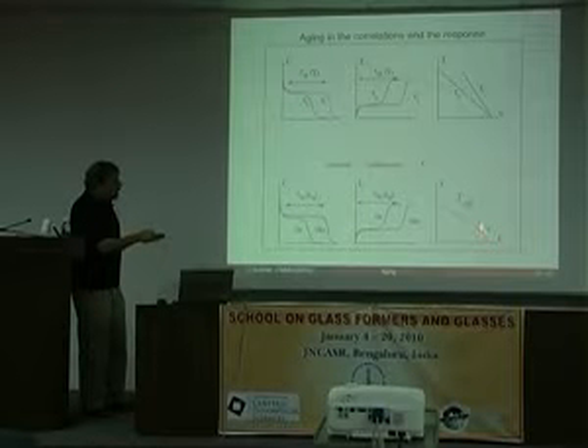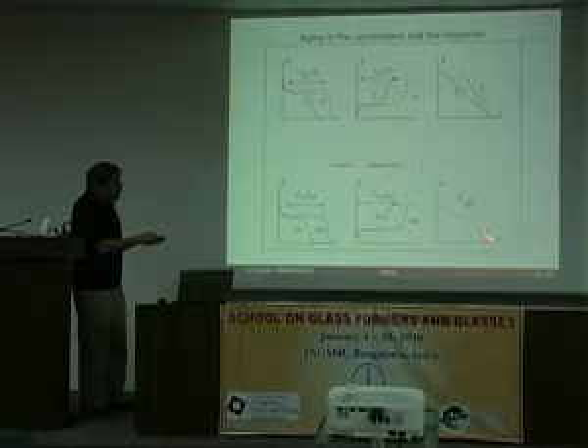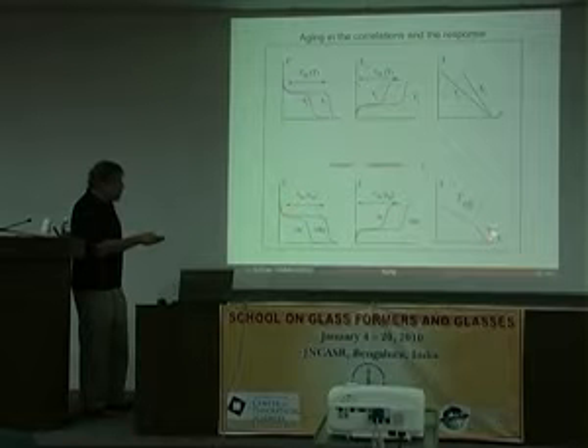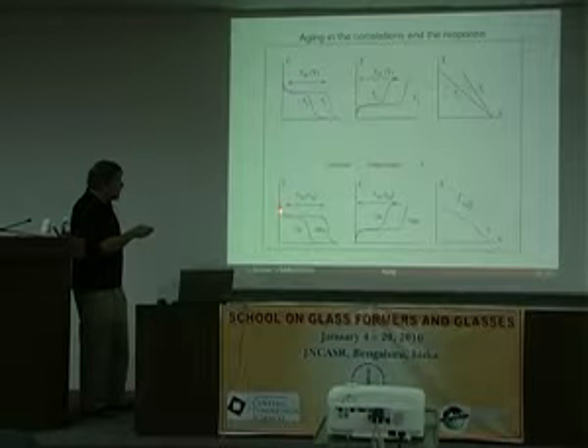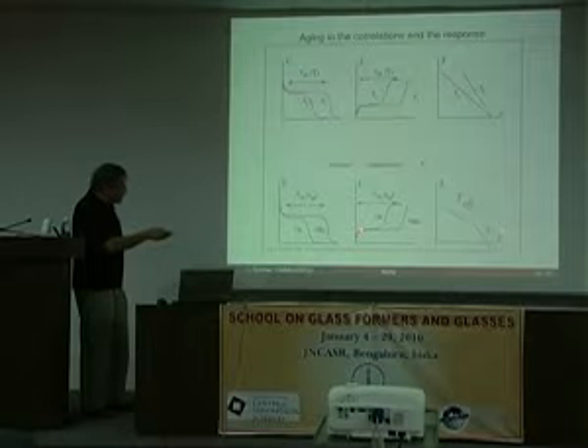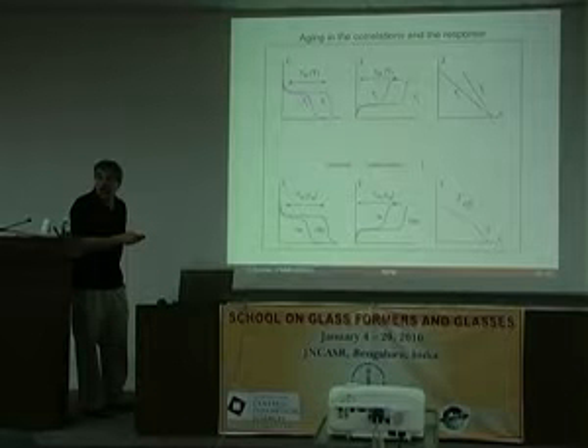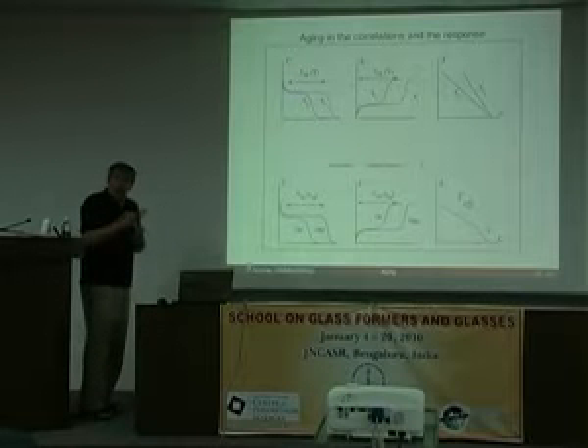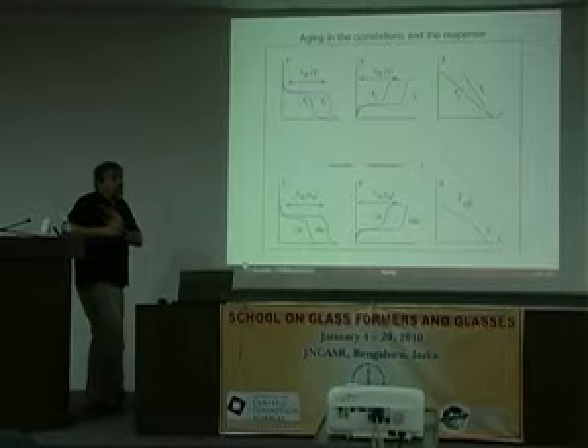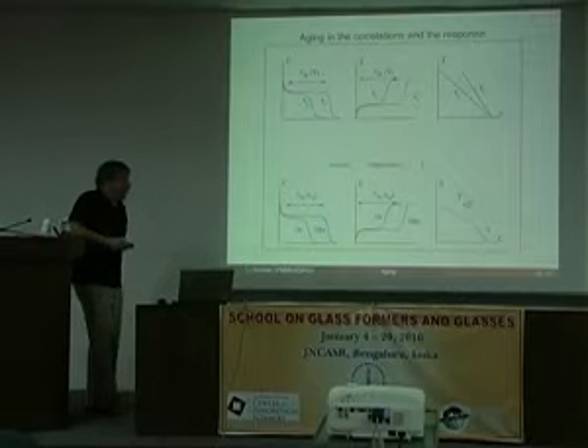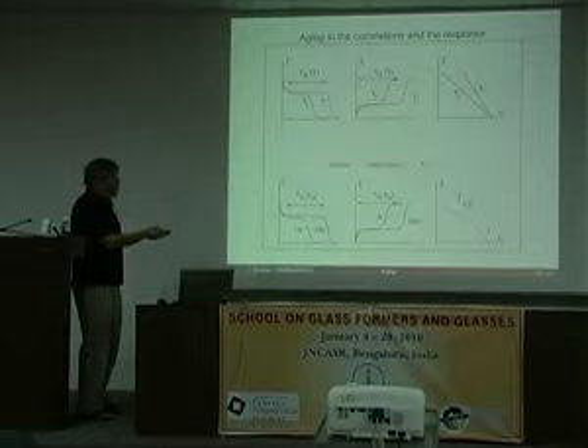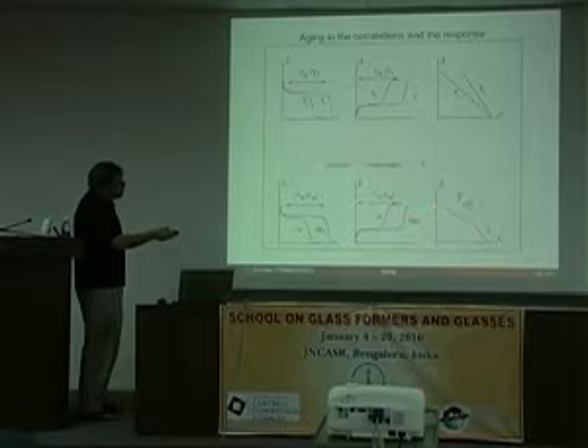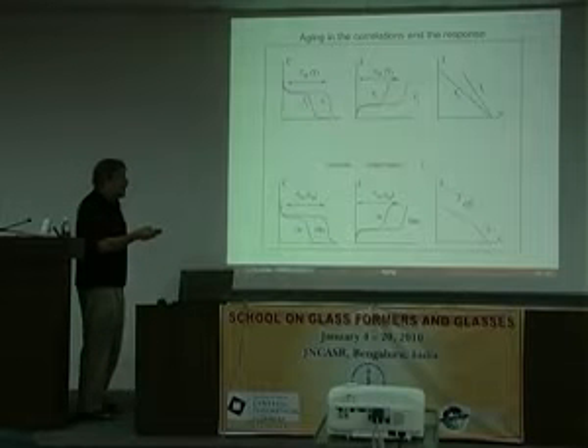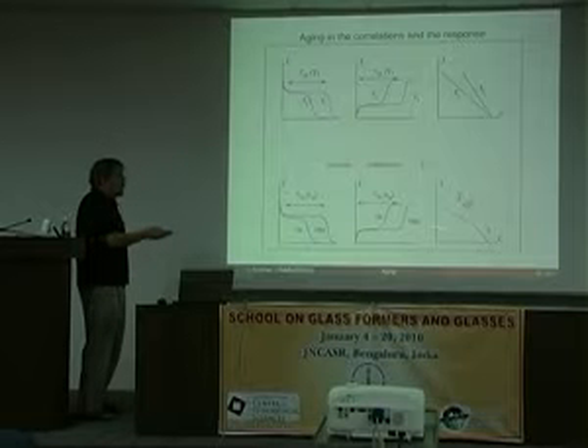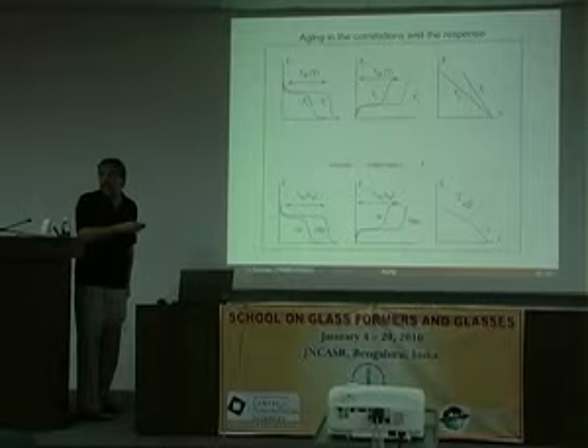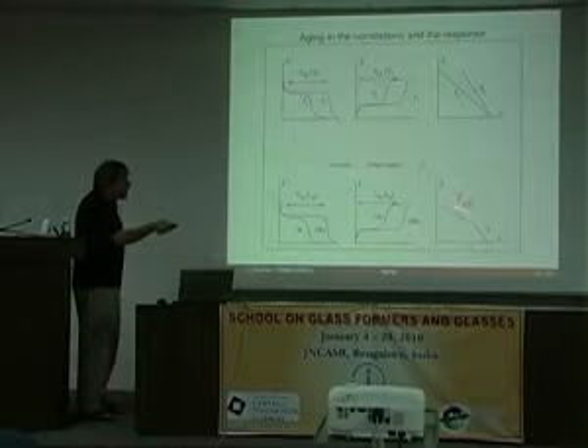And you get, just as in the fluctuation-dissipation theorem, just respecting the usual one for this regime, which corresponds to this part of the curve, and which corresponds to the rapid motion. So the rapid motion behaves exactly as you would expect of a system in equilibrium. But funnily enough, you get a straight line for the other regime. And because it is a straight line, by analogy, you may, if you want, call this an effective temperature.